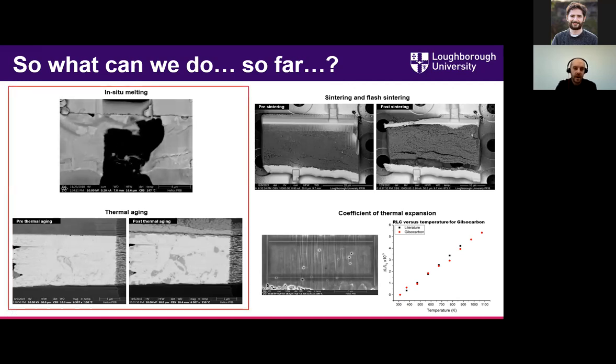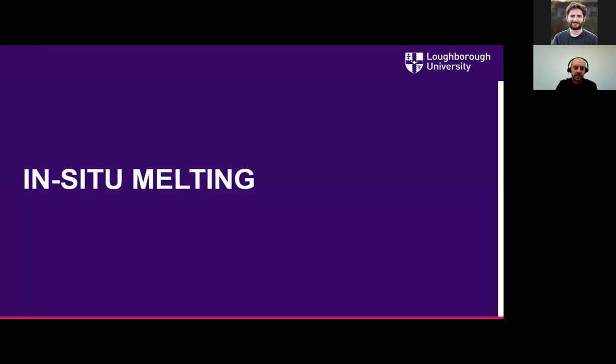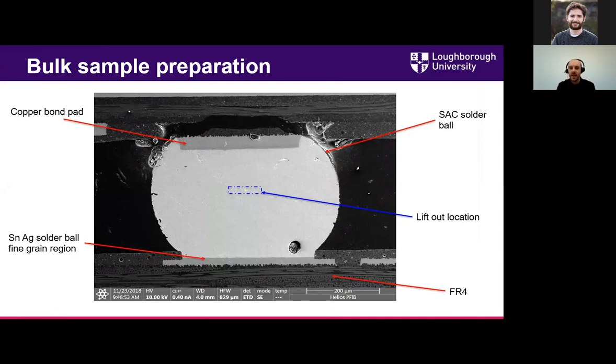So let's talk about this in situ melting. This was essentially just our first test, trying out the hot stage to see what it was like. We'd done some TEM in situ work previously, and we wanted to find out what it would be like using the FIB version. So we took a SAC solder, tin silver copper solder bump, and lifted out a little sample from the center of one of the solder balls